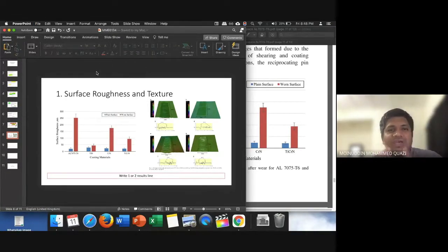Okay, so you have to present what is happening with this surface roughness. Okay, you have to present it. When we do coating of titanium nitride, chromium nitride, and titanium chromium nitride, then the titanium nitride surface roughness was very high after the coating, followed by titanium chromium nitride, and then followed by chromium nitride. Okay, this is for the plain surface. What happened after we do wear testing? After we do wear testing, because our aluminum has not been coated, it undergoes a lot of damage. When it undergoes a lot of damage, then the surface roughness increases too much. So that is why the change in surface roughness for aluminum is too high. So this is something that you have to read from the paper and explain. Okay, so this is property number one, surface roughness.